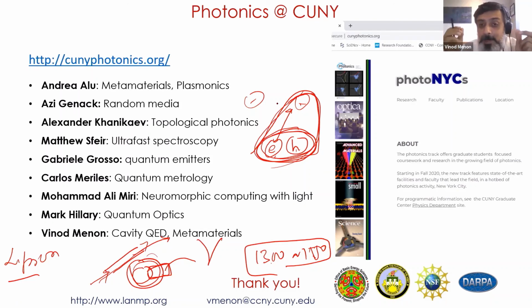They form. But because the binding energy of the electron hole pair itself is on the order of hundreds of meV, you can get 300 meV, for example. You can get the trions to have a binding energy on the order of 30 millielectron volt. And so that's still about room temperature, and especially if you go to low temperatures, you can have them. So that is what happens with trions, and that is why trions can exist.